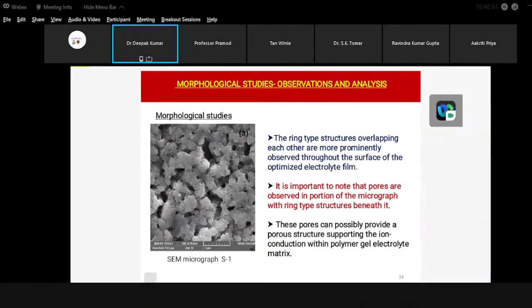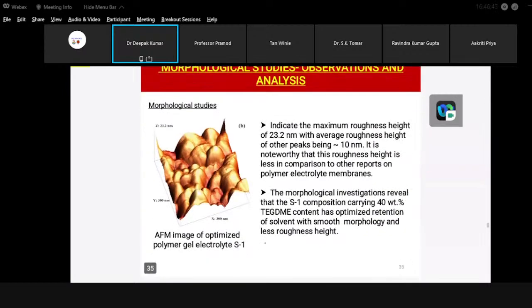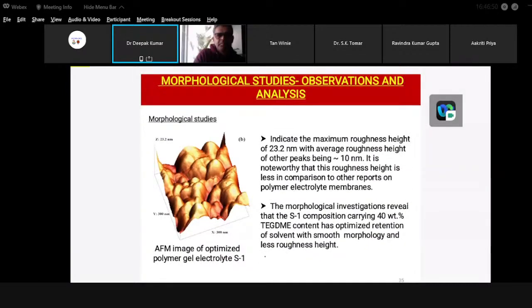We also performed some morphological measurements, and for the optimized electrolytes, a porous kind of structure is seen, which is expected to support the ion conduction within the polymer gel matrix. In the case of AFM studies also, the maximum roughness height is observed to be 23.2 nanometers, with the average height also quite low. Such heights are lower as compared to other reports which we have seen in the literature. This indicates that the surface morphology is quite smooth, and it may be able to sustain and retain more liquid component and give better ion transport properties.